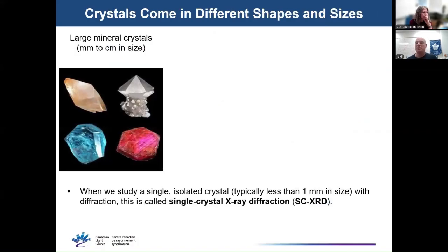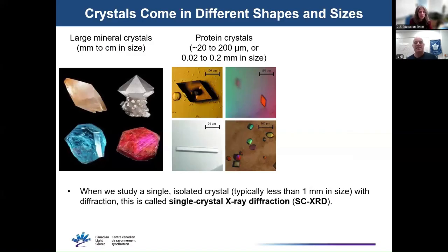There are a couple of different techniques we use to study crystals, depending on the size of the crystal. When we have a large crystal that's easily separated, so that we can look at a single isolated crystal, we use a technique called single crystal diffraction. Large can be a relative measurement. You can see the mineral crystals on the left here on the order of millimeters in size. These protein crystals in the middle figure range from about 20 to 200 micrometers in size, and they are all very suitable for single crystal diffraction.